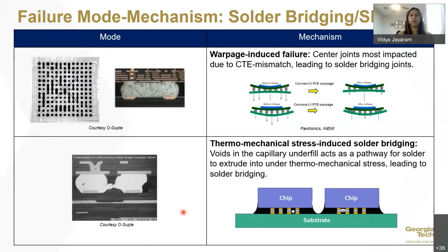Another form of failure is solder bridging or shorts. As you can see, CTE mismatch induced warpage can cause a lot of defects. So it's really important to look at a failure mode and understand what mechanism it is so that it can be managed accordingly. In this case, the warpage induced failure with the same kind of smiley shaped warpage, the corner bumps would see non-wet, open, or solder crack. At the same time, you would have the center bumps that are squished. And because of the large solder volumes typically at board level, these squished bumps would bridge and form a short.